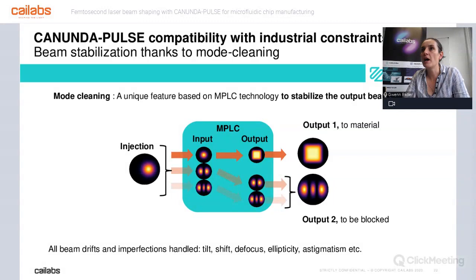We will make a stop now on mode cleaning. As Julien was explaining, when you want to do beam shaping with a monomode laser, you have to have a stable input. If your input is not stable, your shape will be distorted over time, maybe over an hour or 2 hours. You will have to realign all the time. This is not industrial. Femtosecond lasers are very complex to manufacture, and they always show some instabilities, even if very small. It can be tilt, shift, defocus, ellipticity, or astigmatism.